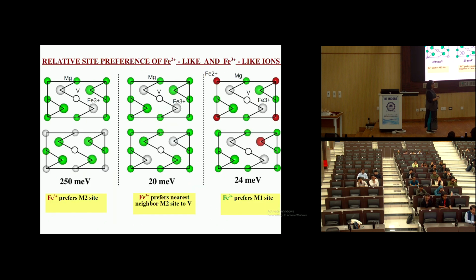So what we found with our total energy calculation again, the vacancy most favorably forms in the M1 site, as I have already mentioned, and the iron neighboring this vacancy site, which is shown here, you can see the chain-like structure, transforms from iron 2 plus to iron 3 plus, and iron 3 plus prefers M2, unlike iron 2 plus, which prefers M1. So iron 3 plus prefers M2, while iron 2 plus prefers M1.